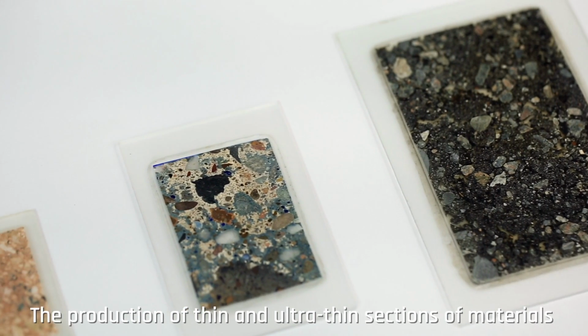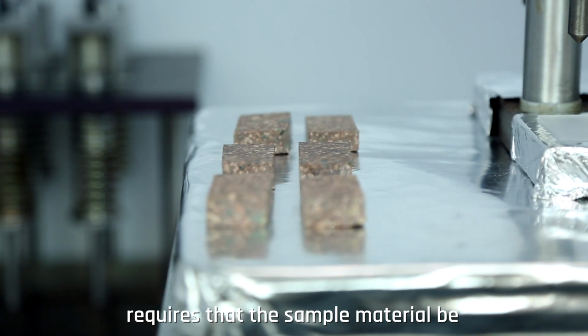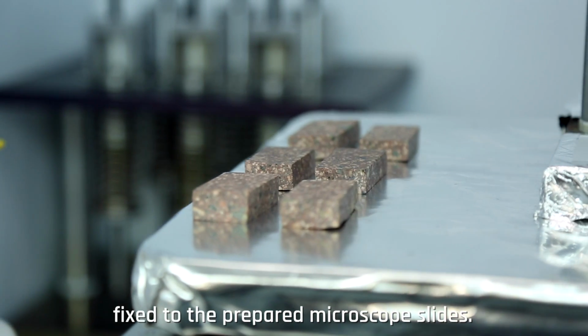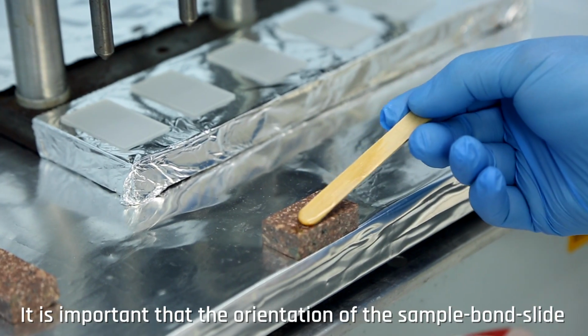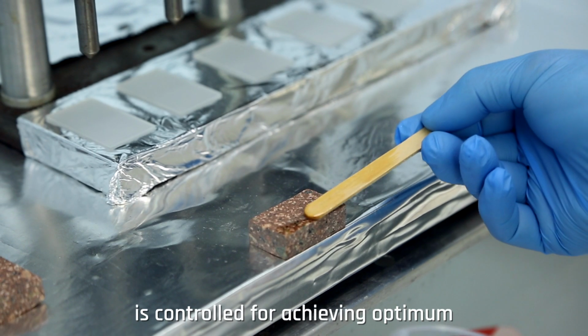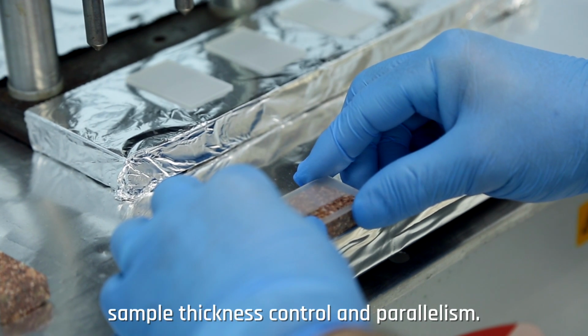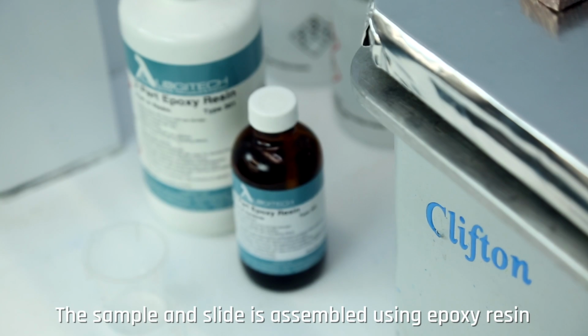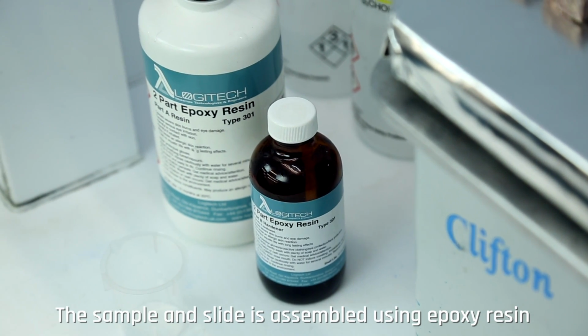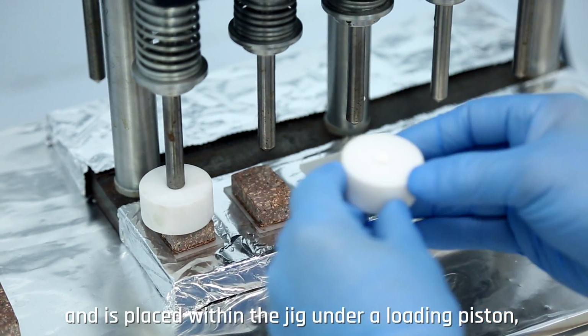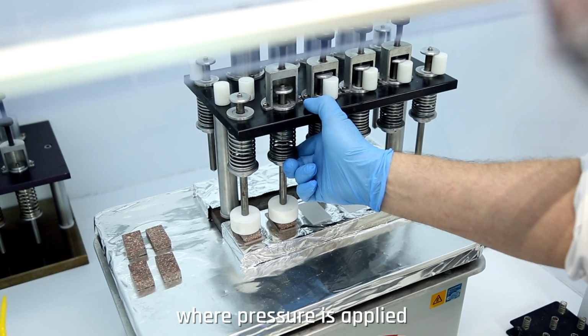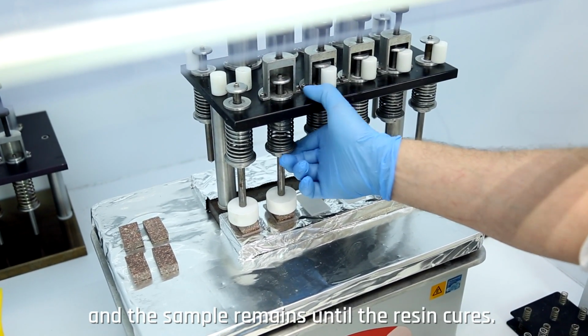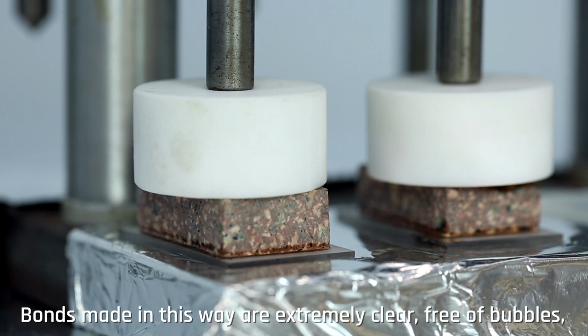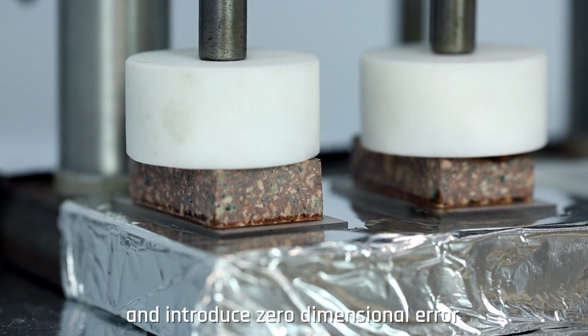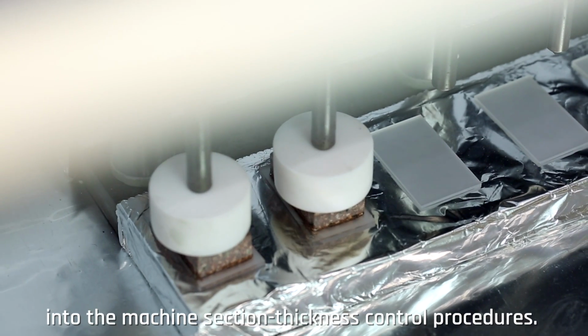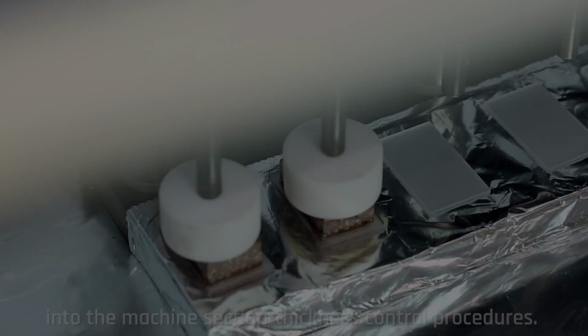The production of thin and ultra-thin sections of materials requires that the sample material be fixed to the prepared microscope slides. It is important that the orientation of the sample bond slide is controlled for achieving optimum sample thickness control and parallelism. The sample and slide is assembled using epoxy resin and is placed within the jig under a loading piston, where pressure is applied and the sample remains until the resin cures. Bonds made in this way are extremely clear, free of bubbles, and introduce zero-dimensional error into the machine section thickness control procedures.